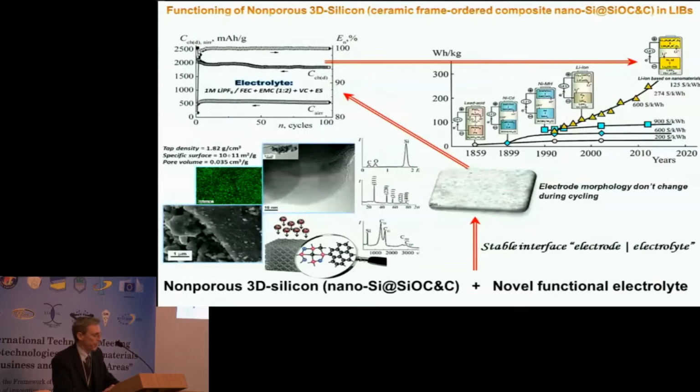The main drawback of silicon-based anode materials is the high volume expansion taking place during the lithiation and delithiation process, which can be up to 280% compared to the original volume. These volumetric changes can lead to several degradation processes. Examples: strong mechanical strains, pulverization, loss of electric contact between the different anode components, and failure in the stability and structure of the anode electrolyte interface. To improve the structural stability of the electrodes around the silicon particles, one usually creates a space that is filled up with void space to accommodate swelling.